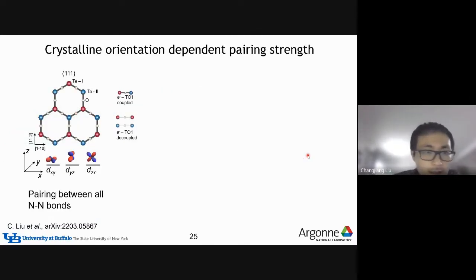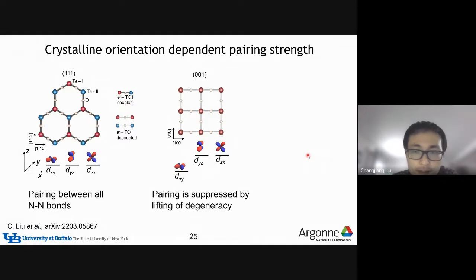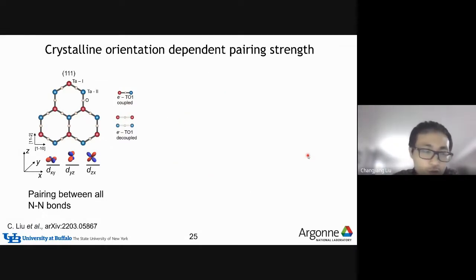So just to give a little more explanation why this mechanism could produce a striking crystalline orientation dependent pairing or superconductivity. This is again the KTO-111 surface, and in this case, the 3D orbitals dxy, dyz, and dxz are all degenerate. They have the same energy. So this means they could couple strongly by the TO1 phonon because they are degenerate. So once there is a TO1 phonon, the electron can hop from one orbital to the other.